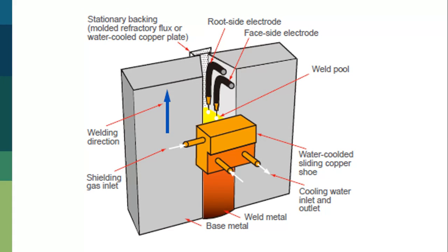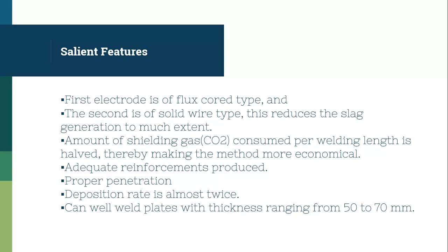Then again, here you can also relate the process again. Salient features. First, the electrode is a flux core type and the second is of solid wire type. This reduces the slag generation to a great extent. The amount of shielding gas carbon dioxide consumed per welding length is half, thereby making the method more economical. Adequate reinforcement is produced. Proper penetration, and deposition rate is almost twice. It can weld plates with thickness ranging from 50 to 70 mm.